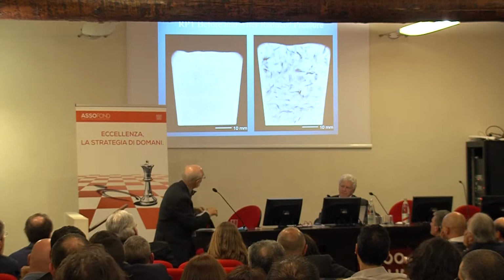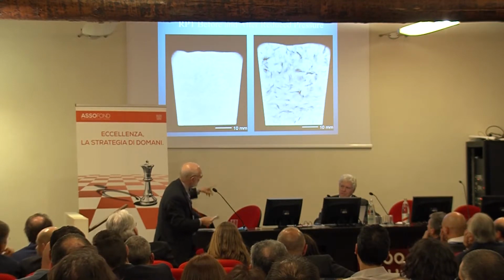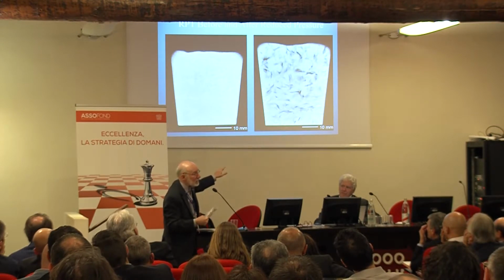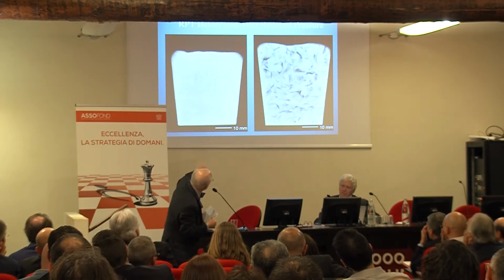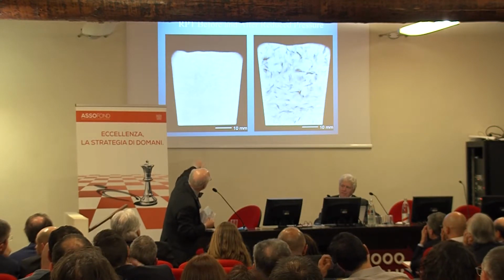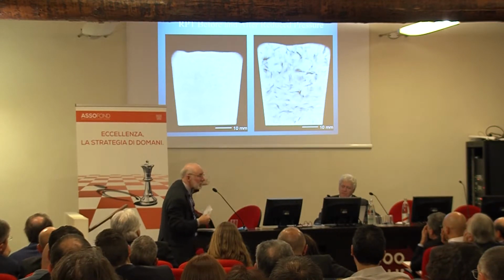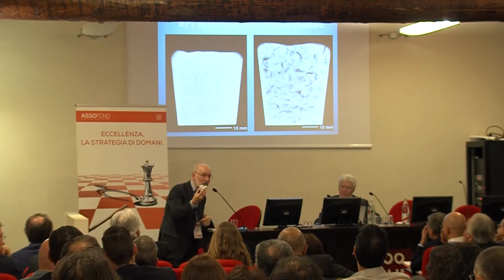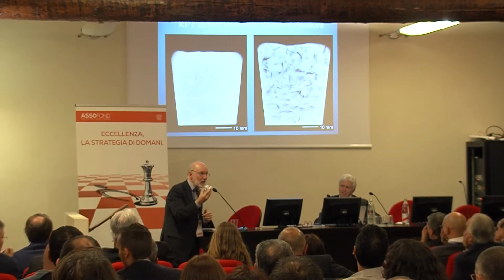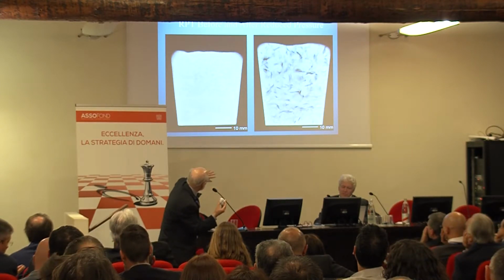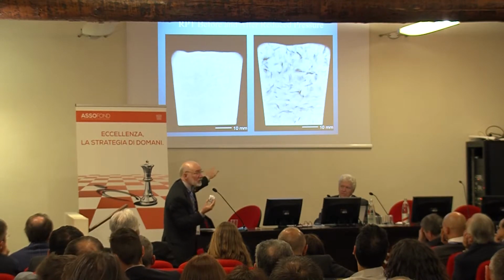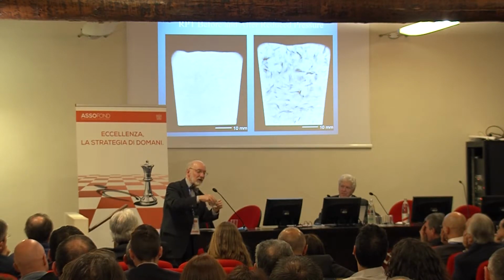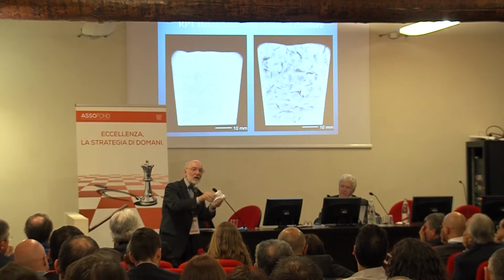And sure enough, on the right you can see that we do have cracks in the liquid that we can see now. But interestingly, look carefully at the left figure. The tiny shadows. Those are the compact bifilms. Come all the way through the material, you can see them floating about. But as the pressure comes down and the pressure builds up inside here, this inflates it.